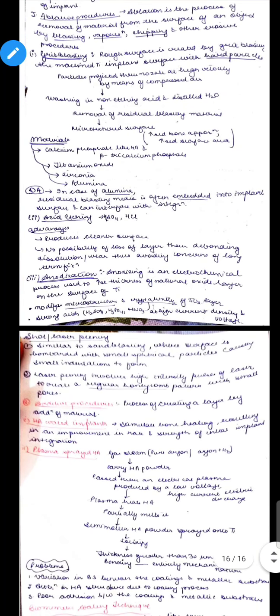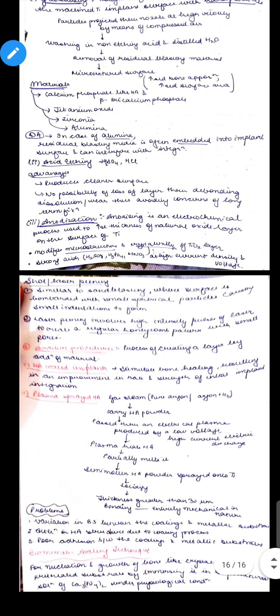Then coming to the second process, that is acid etching. In acid etching we prefer strong acids like sulfuric acid and hydrochloric acid. They provide a cleaner surface, so no residual materials will be left, so there will be good integration. There is no possibility of loss of the layer through debonding, dissolution or wear, thus avoiding concerns of long term fixation. Anodization: anodizing is an electrochemical process used to increase the thickness of the natural oxide layer on the surface of titanium. It modifies the microstructure and the crystallinity of the titanium oxide layer. Strong acids are used like sulfuric, phosphoric and nitric acid, with high current density and voltage.